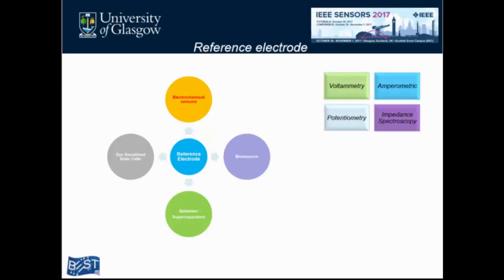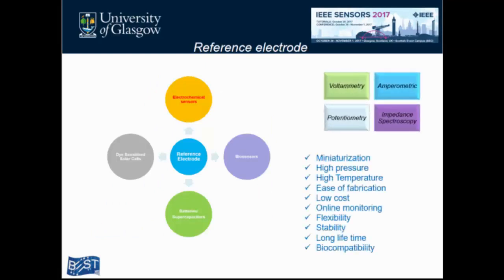So, why a reference electrode? In electrochemical sensors, we mainly work on sensitive electrodes, in sensitive field effect transistors, and on miniaturization of the device. We can fabricate sensitive layers as nanotubes and nanostructures, at the nanoscale. But the major problem in electrochemical sensors or studies is that they require a reference electrode. Commercially available reference electrodes are mainly glass-based electrodes. The problem with glass-based electrodes is that they contain a KCl solution. With time it will dissolve and leak out, so we have to fill it again, and at high temperature it will break, and it is not possible to miniaturize.